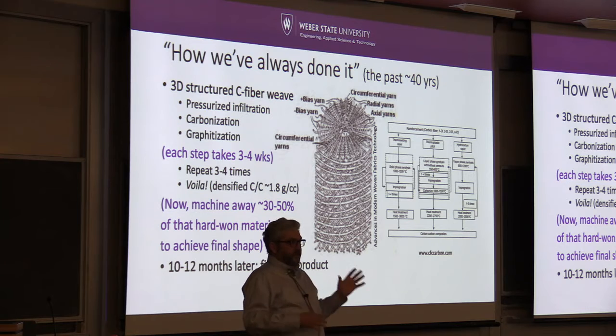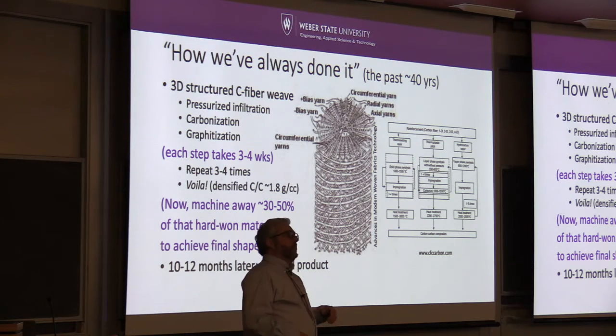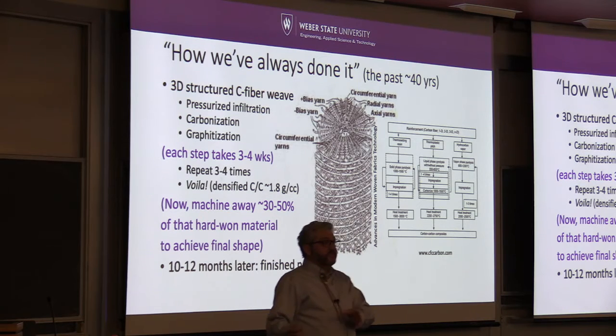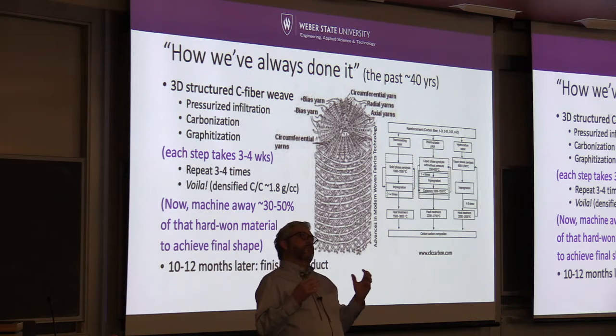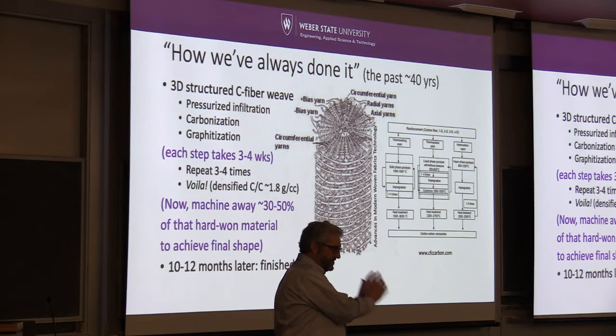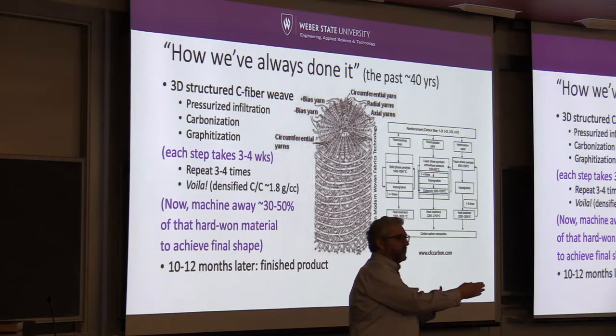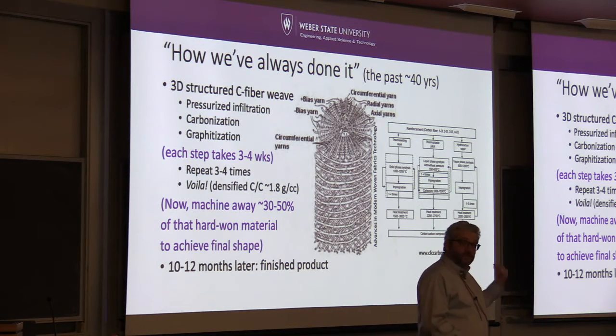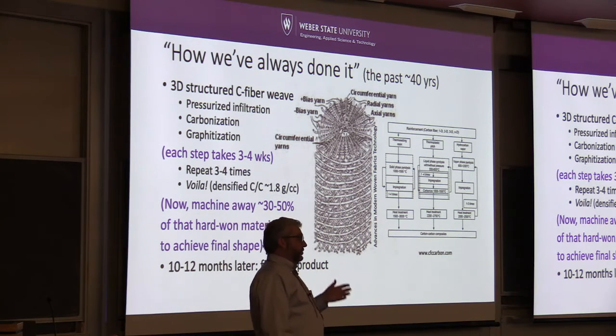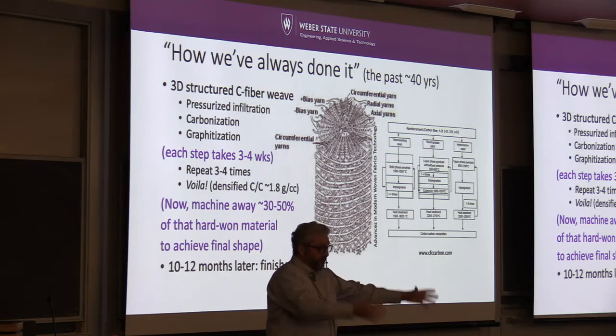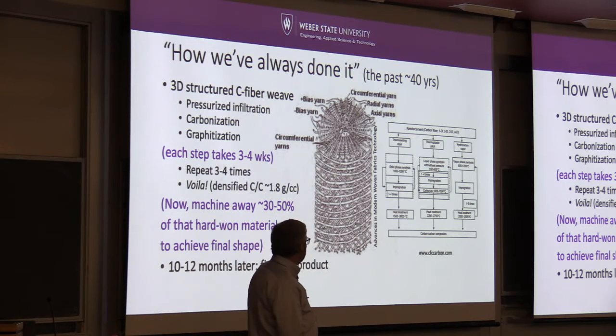But if you then take this thing out of the batch, you have to cure it now, and so there's a carbonization process which drives off some of the volatiles, and so it's just a heating process. It may be under vacuum, and then it goes into a graphitization process where, think about this, you need to create ingress cracks in the stuff you just polymerized so that you can go through the process again and have an ingress path for the next step, because you don't just do this once. If you do it the first time, when your target density is about 2 grams per cc, the first time you might only get 1.5 if you go through that cycle of infusion, carbonization, graphitization. So those are 3 separate vats, the last of which is this big giant vacuum chamber heater.